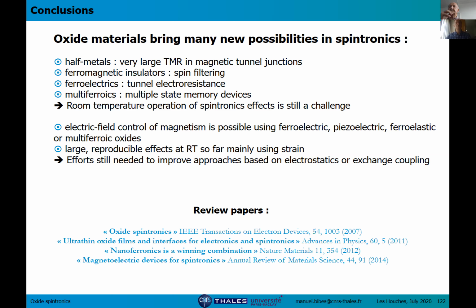You can introduce ferromagnetic insulators, most of which are oxides, in the barrier, and you get spin filtering, and in principle, you should get very high TMR. It's not exactly conclusive yet, but finite TMR has been observed. Ferroelectrics as tunnel barriers can produce very strong tunnel electroresistance effects. I think the largest values up to now are maybe 10 to the 4, 10 to the 5 off-on ratio, and they can be used as electronic synapses for neuromorphic computing.